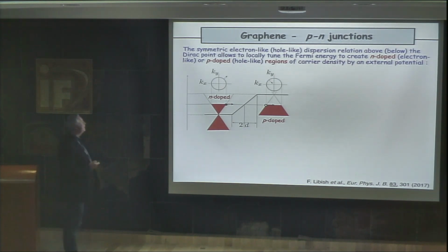The phenomenon that I wanted to explain is the evolution of Dirac fermions in p-n junctions. The way you can create a p-n junction in graphene is very easy because you have this Dirac cone. If you take these two cones, you have exactly the Dirac cone. The Fermi energy is exactly at the middle, but if you move down the Fermi energy, if you n-dope your system, you will have the Fermi energy in your upper cone, and if you move up the Fermi energy, you will get your Fermi energy in your lower cone. So this is exactly the p-n junction that we have here.